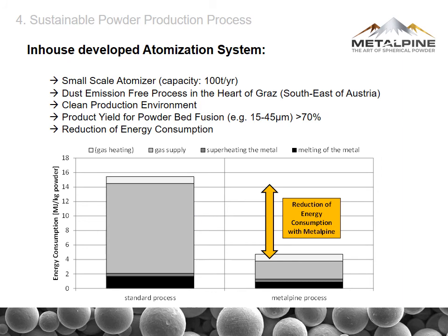With our in-house developed atomization system, we achieved a high reduction of energy consumption. You can see here the main contributors to energy consumption. The first one is the melting of the metal. Then we have got the superheat of the metal. If you want to, also the gas heating plays a role. But the main energy consumer is the gas supply, the inert gas supply. And with our in-house gas recovery system, we can reduce the energy consumption by more than 70%.